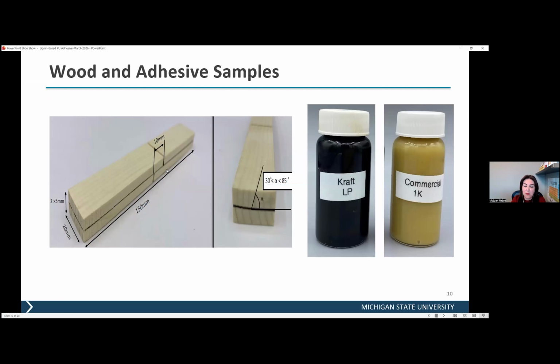There is a very strict requirement for the test samples that we are preparing. The size is 15 centimeters by 2 centimeters, but they also care about the grain orientation of the wood. The grain orientation has to be between 30° and 85°. That's the angle that we need to use.